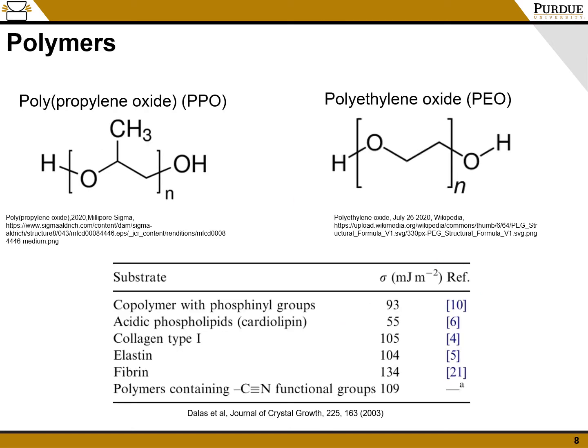So a potential avenue to explore is how polymers can add in nucleation sites into salt hydrates. In particular, I looked at polypropylene oxide and polyethylene oxide. Both of these have an ether oxygen on them, and that's a polar functional group. And what it does is it pulls in the metal cations from the salt hydrates and starts a nucleation crystal, which kicks off the nucleation process.